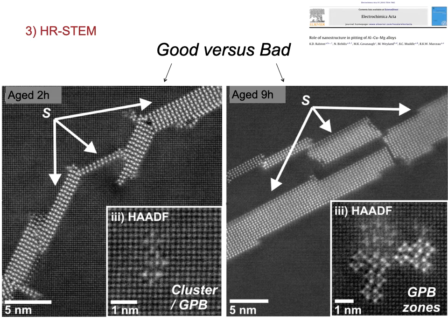So the result actually shocked us, and these are great aberration corrected STEM images, by the way, that show the difference on the left between a pitting immune microstructure and on the right a pitting prone microstructure. And it was a subtle change in the width of a precipitate that led to that jump.